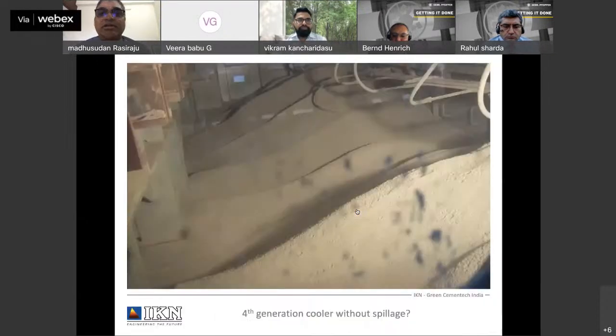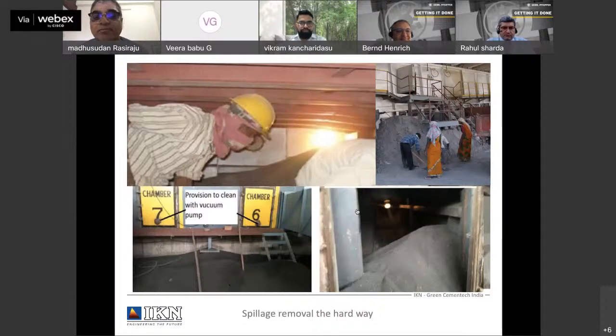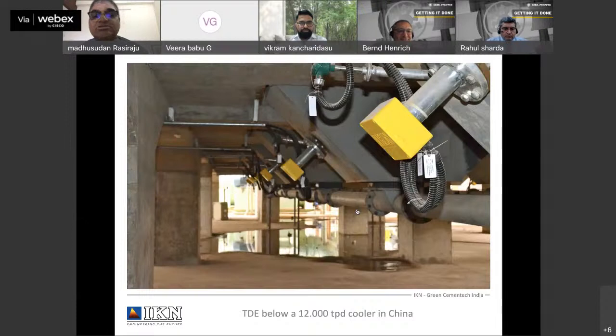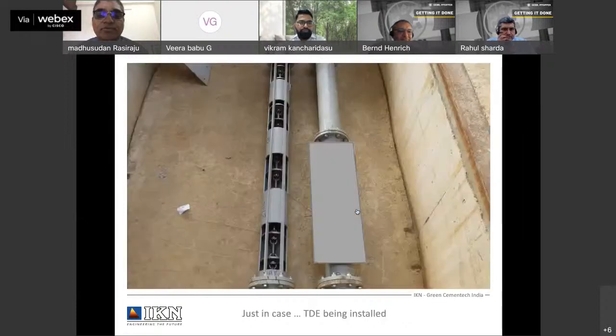And then we have the TDE, it's called a dust removal system. Normally what happens is the 4th generation coolers or walking floor coolers claim that there is no spillage, but we have found that the spillage is being removed from the underhead compartment in a very hard way. Whereas in our case, this is removed by means of the TDE, the tube dust extractor, which looks like a very simple conveyor of about 4.5 inches diameter. Inside the tube there are discs connected by a chain. This conveyor need not run 24 hours a day. In a cooler, it normally works between 40 to 80 minutes in a shift. So whatever dust is accumulated inside the underhead compartment will be taken out by this tube conveyor in IKN coolers.